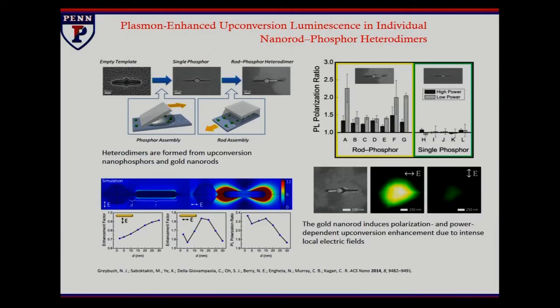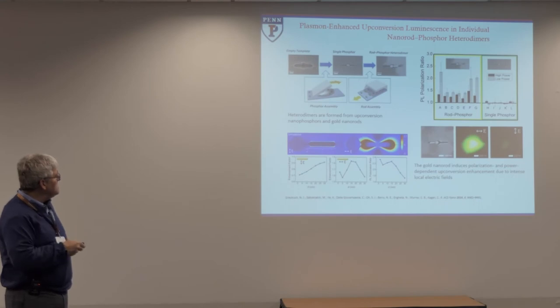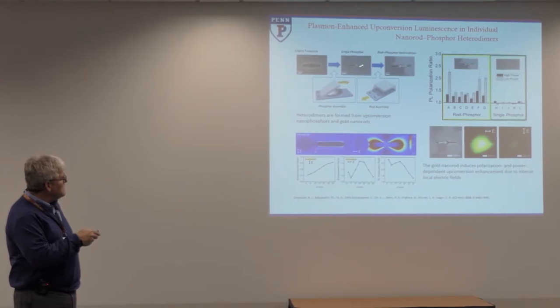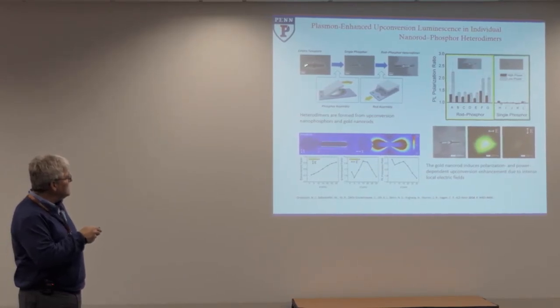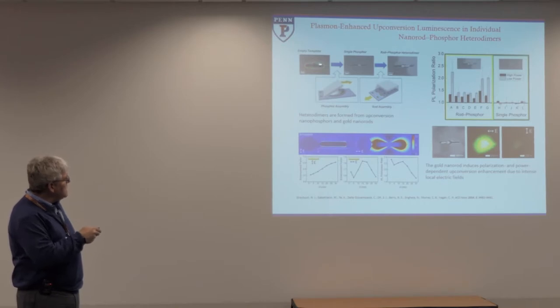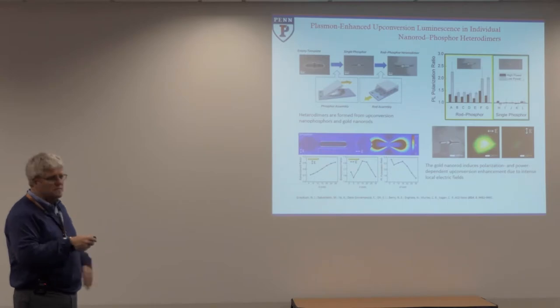assembly using these techniques. Probably the best developed methods are things that work on hundreds of nanometers to micron scale. There are some things that become a little more challenging as you move down to just few nanometer scale. But this is a way to take advantage of some of the lock and key placement to study the same effect. So in this example, we can use lithography to create a structure in which there is space for one of the larger emitter particles to fit, but they can't fit into the arms. And the arms are designed so that they're the right size to put one of these gold particles, for example, in the placement.